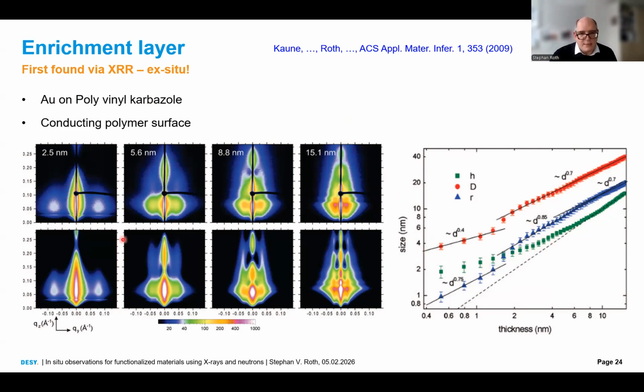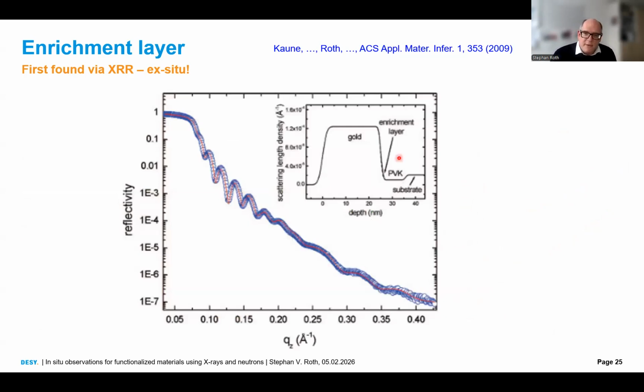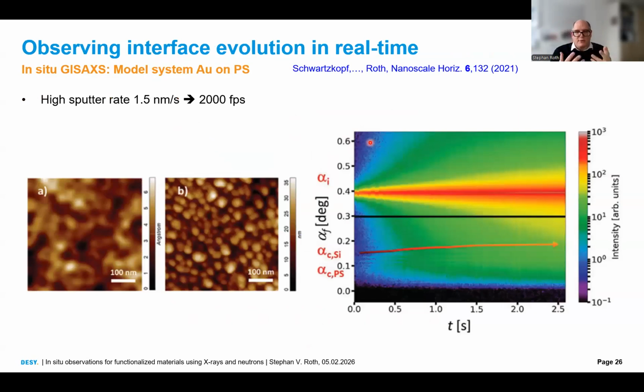Again, here you see the experimental data, the simulated data, and we can go into all details of the growth laws of the nanoclusters with distance, radius, and height as a function of thickness. But what is more important, when we made an X-ray reflectivity measurement, we found an enrichment layer between the gold top layer and the polymer sublayer. And this was the first time this was found for solar cells. And this explains somehow why the electrode worked, because you have a diffusion layer. So the band gaps go smoothly from the semiconducting polymer to the gold electrode and thereby enhance the charge carrier extraction. And what we asked at that time, this was purely ex situ, you see this is 2009, can we see maybe how this gold enrichment layer really grows? And this is what we did then.